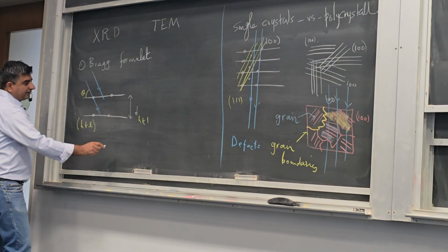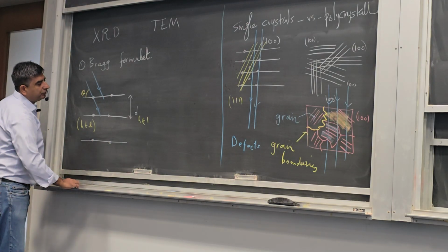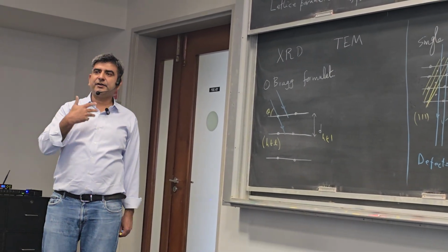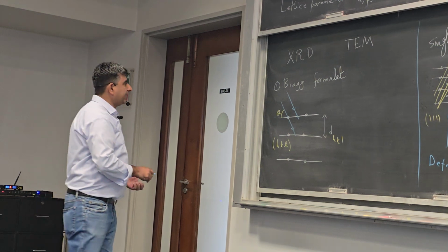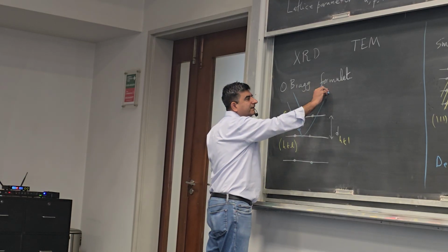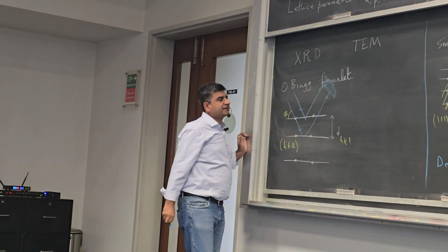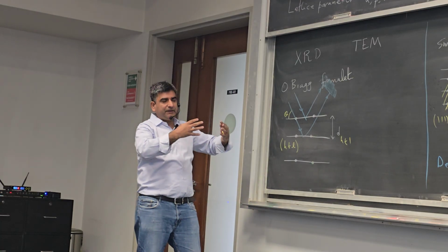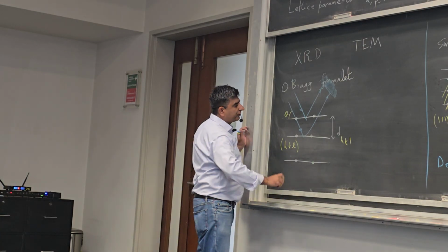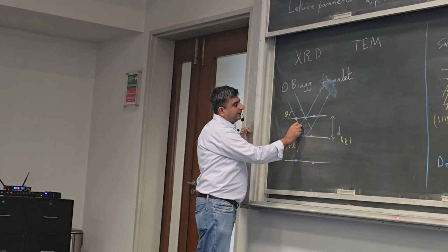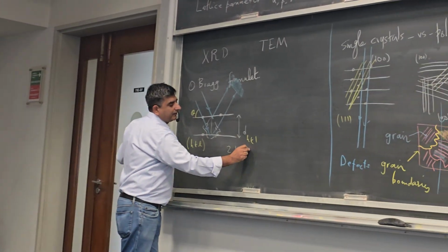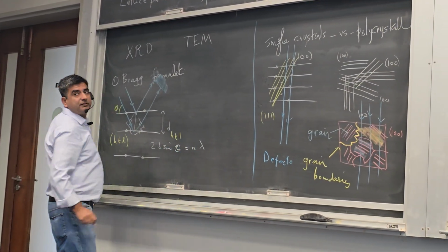Now what's going to happen is, if we view these planes as reflecting mirrors for X-rays, and we take a reflection oriented approach to diffraction, then these X-rays will be reflected from each plane, and depending upon whether we see an intensity here, whether we see some X-rays being emitted, they will only be emitted if these waves are in constructive mode, they are constructively interfering, and that's going to happen when the path difference, this path difference, which is 2d sine theta, is some multiple of lambda.